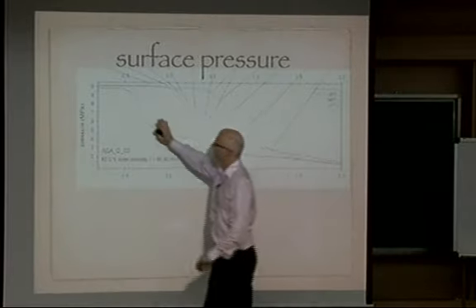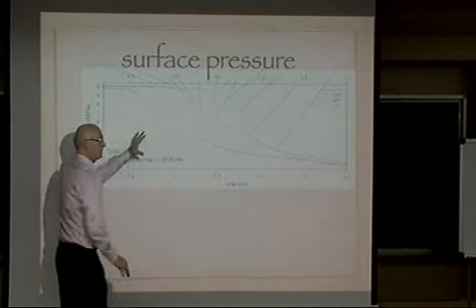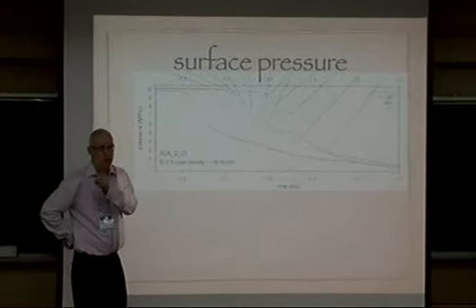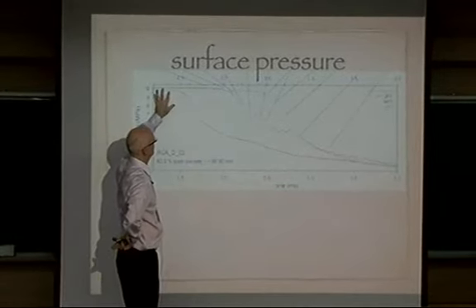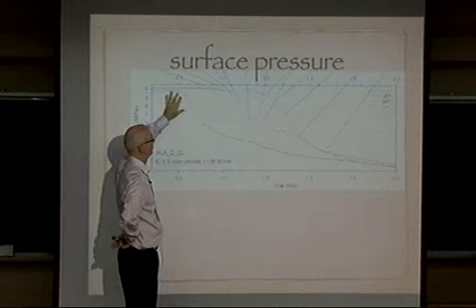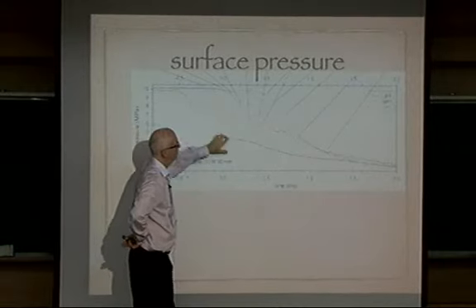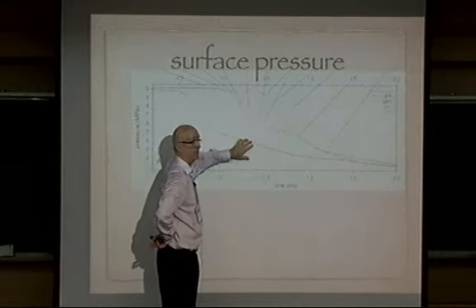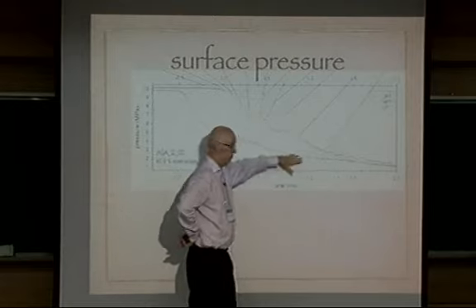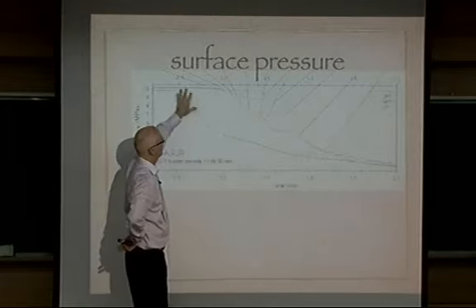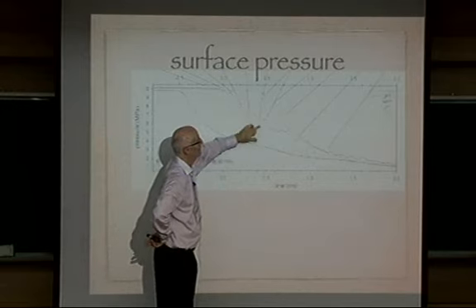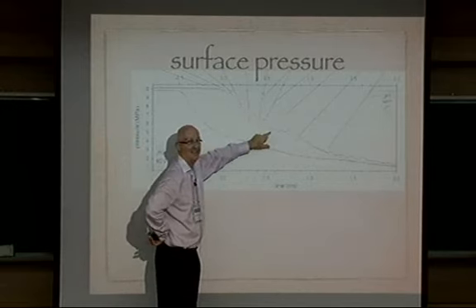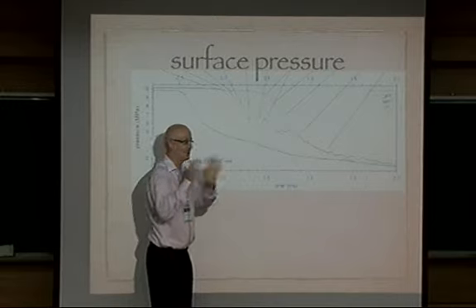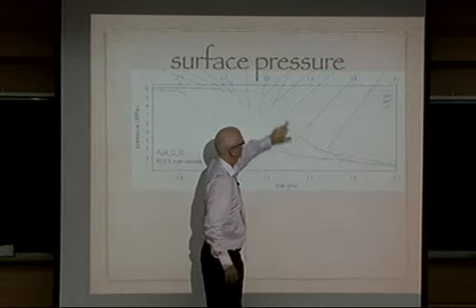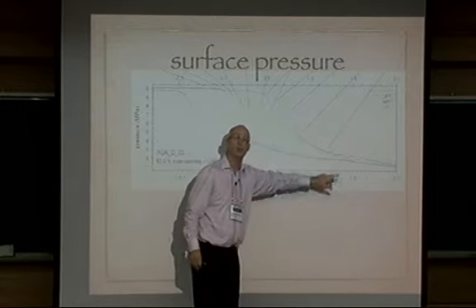But as I said, there is one more parameter, and if you look at the pressure, here's pressure versus time measured from that experiment, and 3 probes. One probe is at the top, so here's the gas rarefaction wave coming down, meeting the sample, being modified a bit here because everything's breaking and lifting off, but basically dropping roughly exponentially. And here's the probe in the middle. Here's some broken bits going by, up and down, pressure going up and down, the bits are going by, and here's the bottom. Finally, it's broken off at the bottom as well, and the pressure there drops as well.